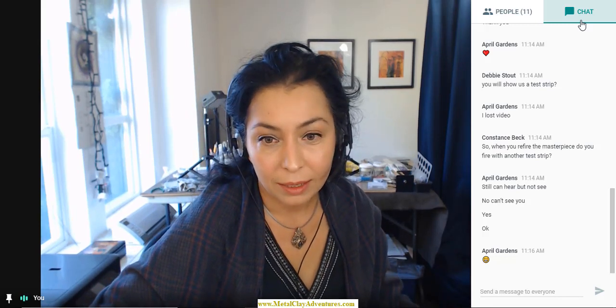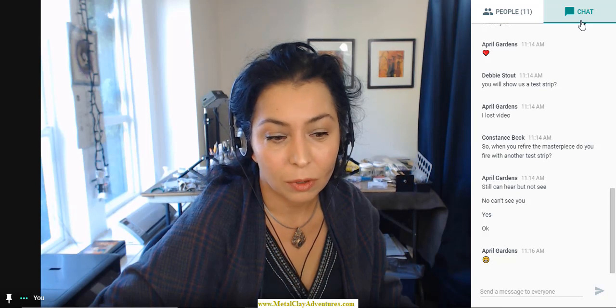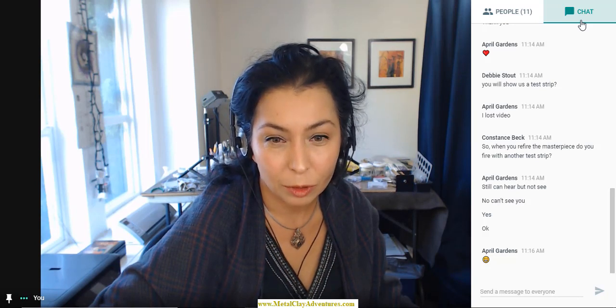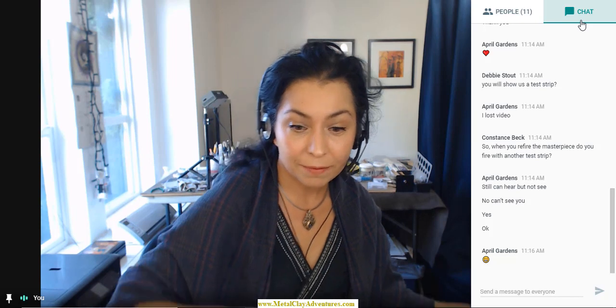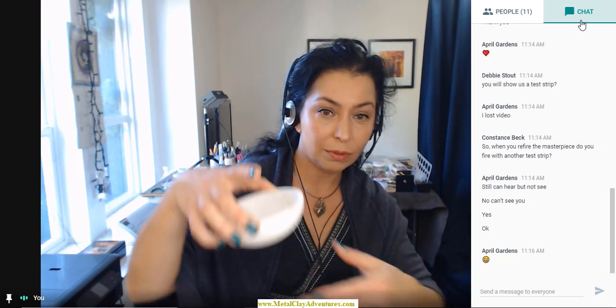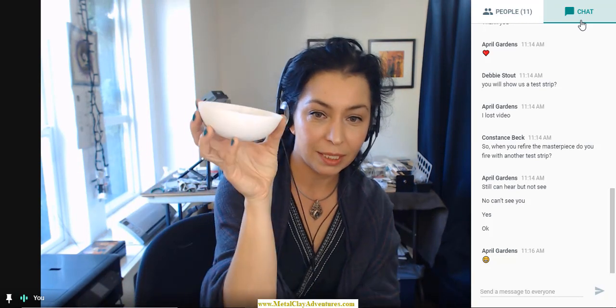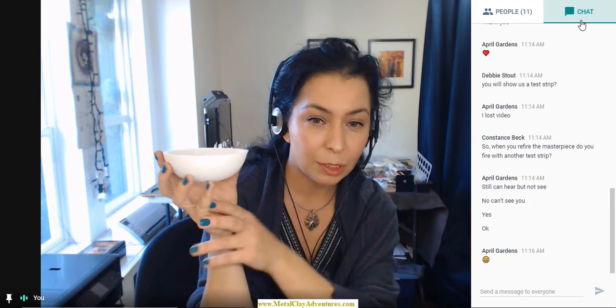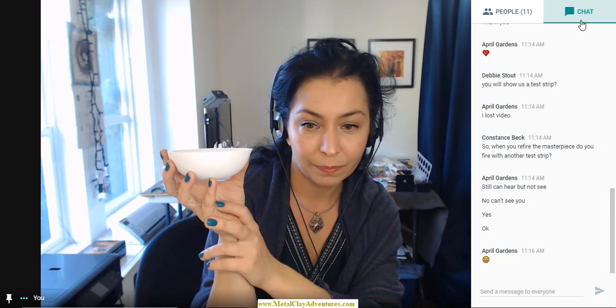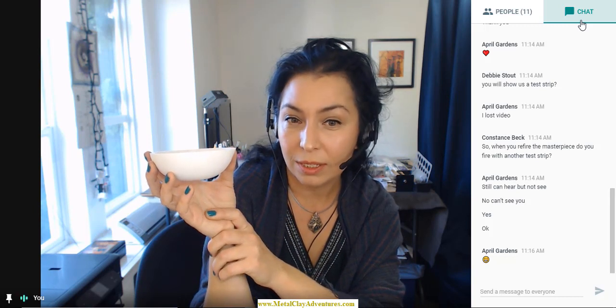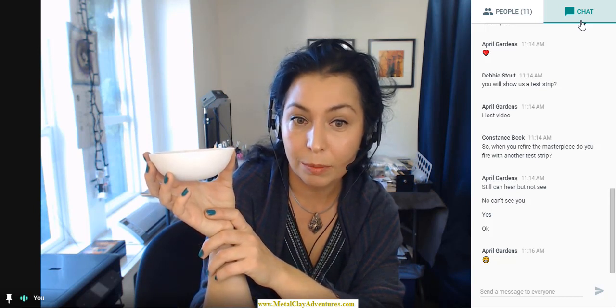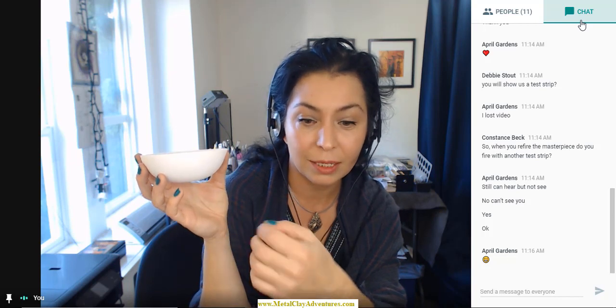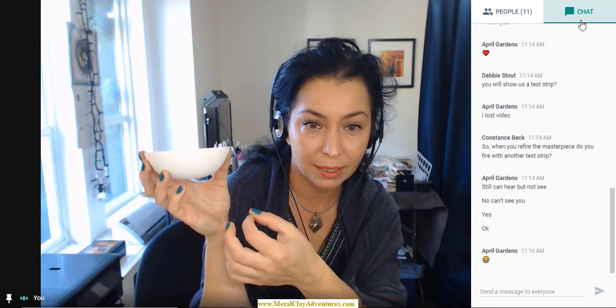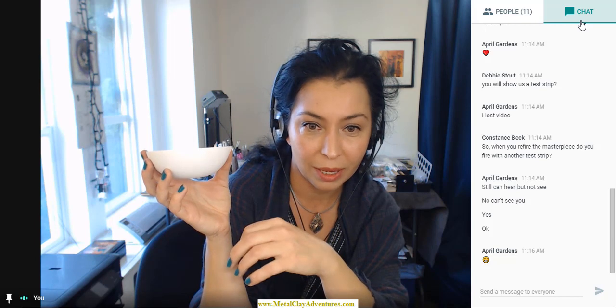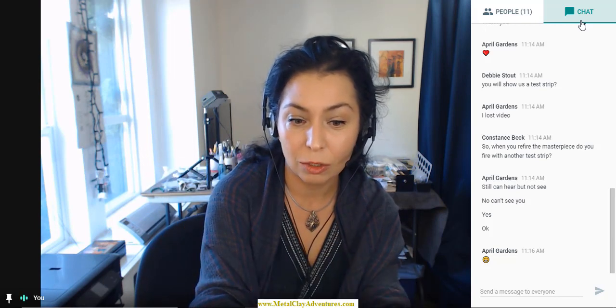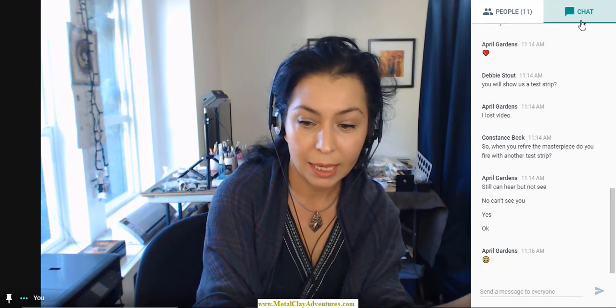You can fire using different support. My favorite support is to use a crucible for melting and to fill it with alumina hydrate. As a wonderful support works vermiculite as well. I just don't like it because it pits the pieces. You can see the pitting on the back of the pieces, and it takes lots of refining afterwards.